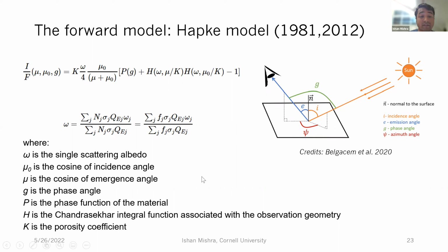And when you have many things in the mixture, if your regolith is made up of many things, as is true for solar system surfaces or any planetary surface, you take sort of a weighted average. So you're based on the fraction of your given species, its cross-sectional area, and something called the extinction coefficient, which is assumed to be the same for most species. So you get sort of an average single scattering albedo that goes into your equation here. And then I described the observational geometry parameters.